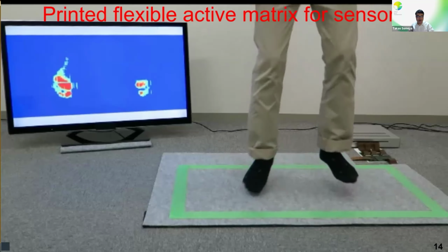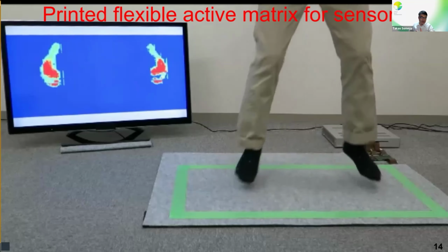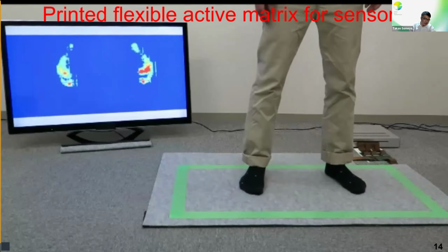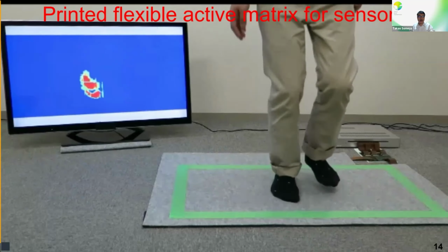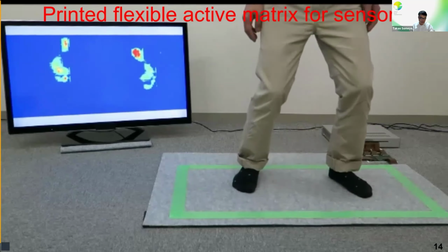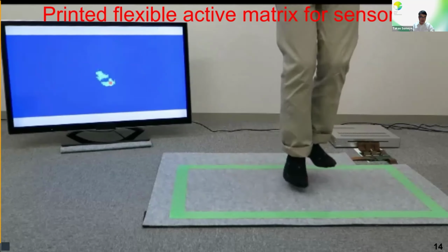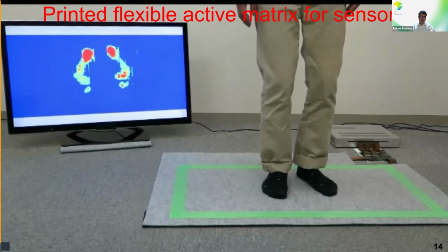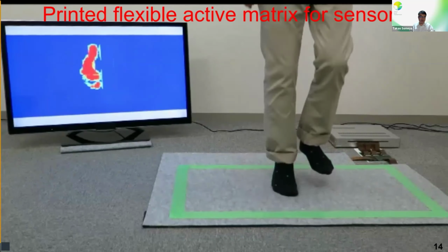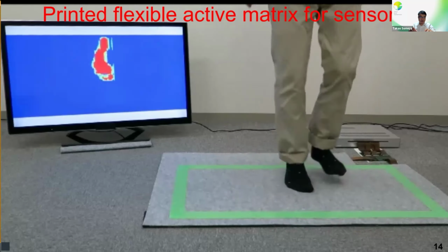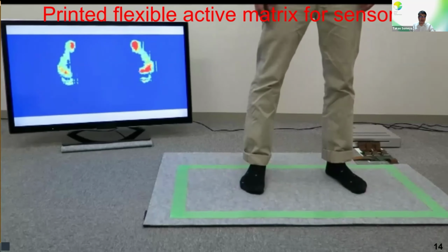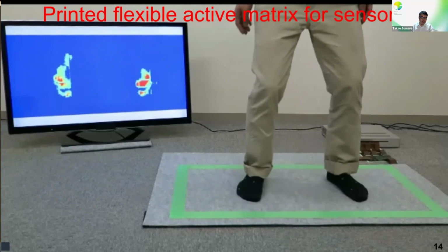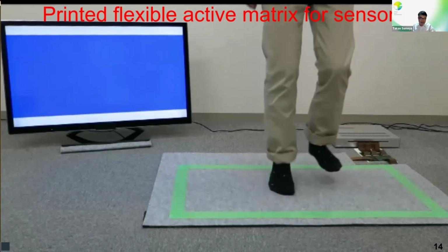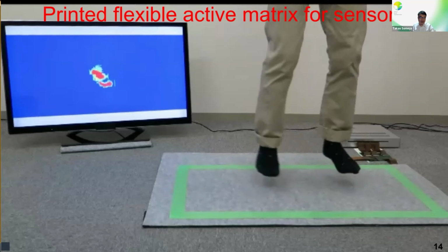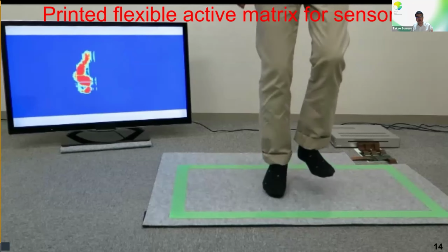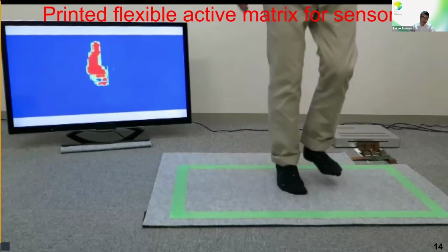And this movie shows you how our device works. And it doesn't look like flexible devices, but those kind of high resolution active matrix is usually manufactured on glass substrate, but glass is fragile. So jumping should cause the device failure. But because our device is manufactured on plastic film, it exhibits amazing durability while maintaining the high spatial resolution and also high data readout.